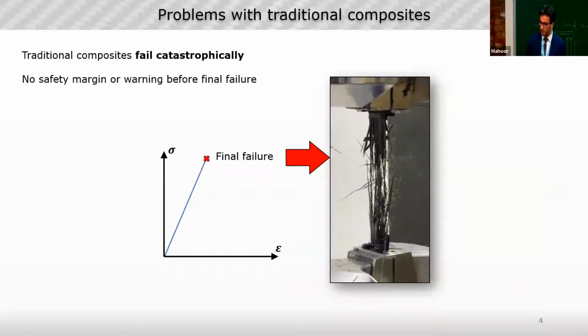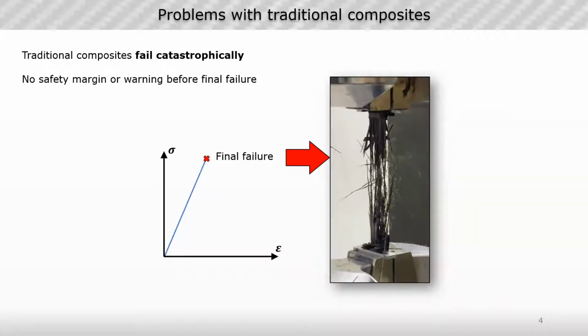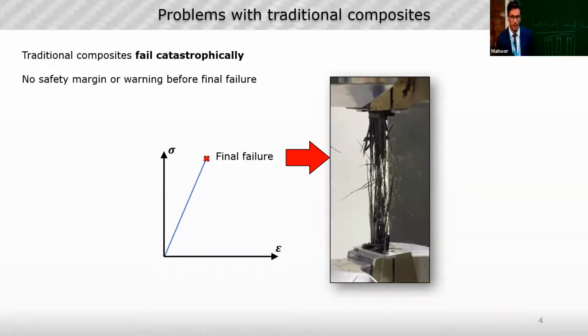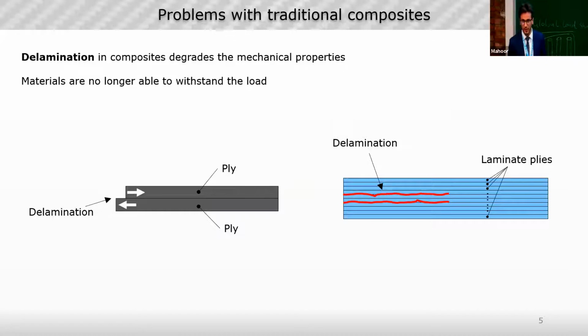What's the problem with composites? They present brittle behavior after a linear elastic behavior. They fail catastrophically. And this is of course an issue from the safety point of view. So there is no safety margin before the final failure, something that tells us that this material is going to fail, and let's do something to avoid it. So sometimes this failure could be unexpected.